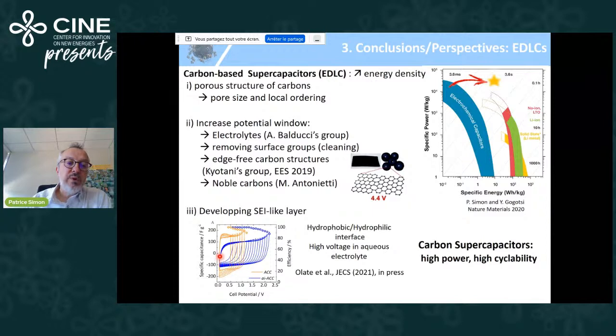If you coat, you design a SEI passive layer onto this porous carbon, you extend the voltage window up to 2 volts. You lose a little bit of capacitance, but you can increase largely the voltage range. And this is definitely, in my opinion, a way to go. But carbon-based supercaps will obviously always have lower energy density than batteries, but high power and high cyclability.